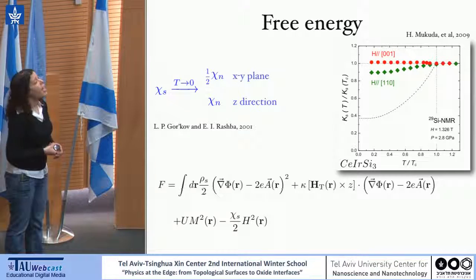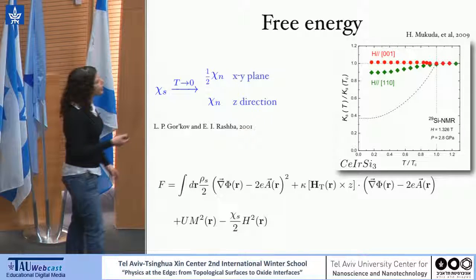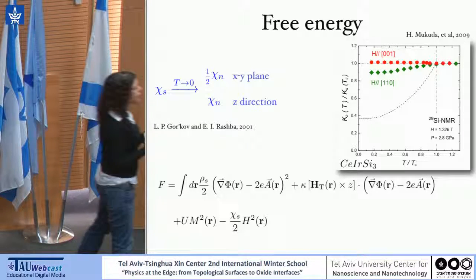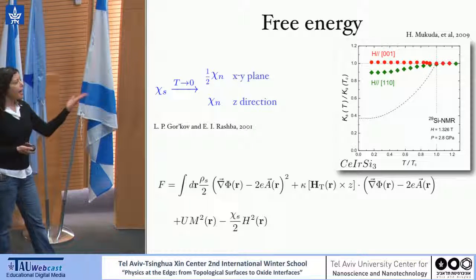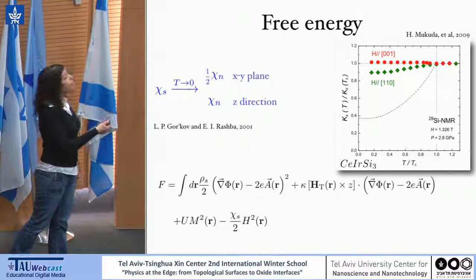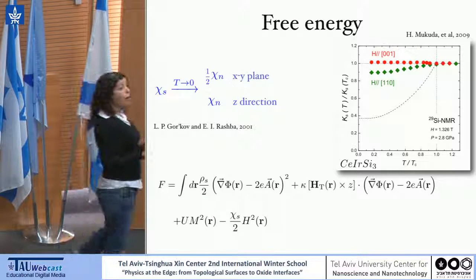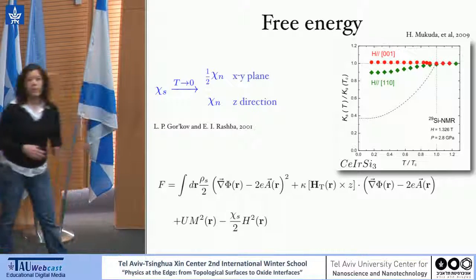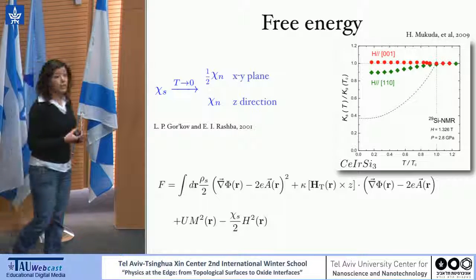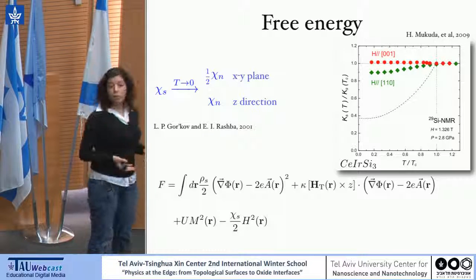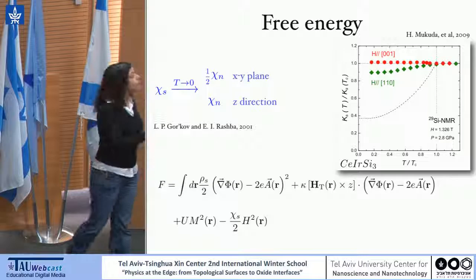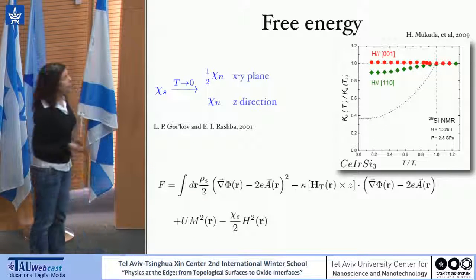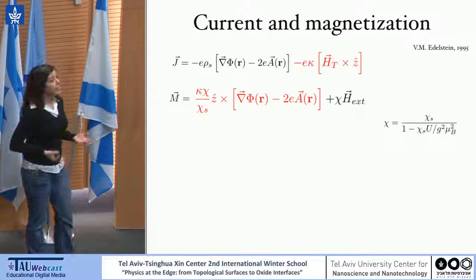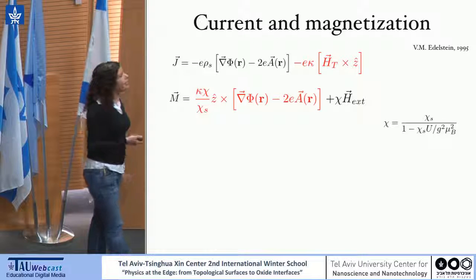Okay. We can even simplify this free energy further and look at the continuum limit. Now we can ask what is the effect of spin-orbit coupling on properties such as the critical current of the system and the magnetization, which is now non-zero inside the superconducting state. And that is because the spin susceptibility is non-zero. So let us look at the superconducting current of the system.